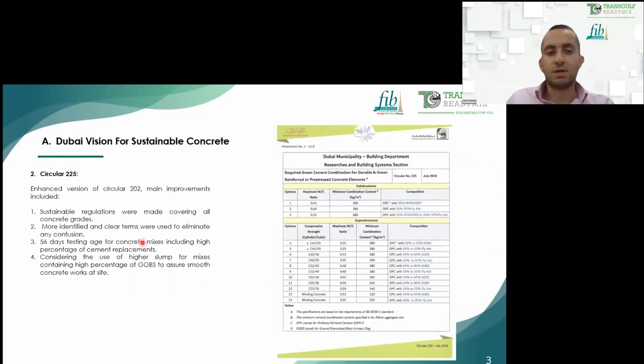The main points enhanced in this one: sustainable regulations were made covering all concrete grades. As we saw before, the previous circular did not include the grades below 25 and beyond 40. This one includes all the grades. All the concrete mixes must comply with this, and the usage of supplementary cementitious material is a must, including the blinding, as we can see here. It includes two options for the blended concrete, with GGBS or with fly ash.